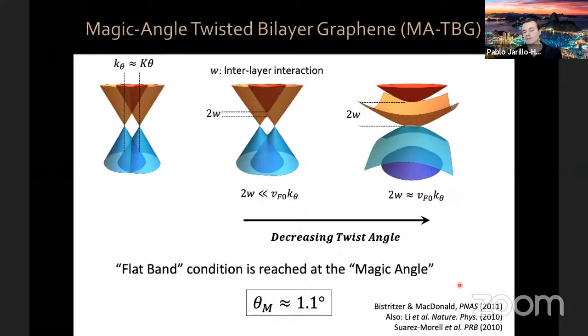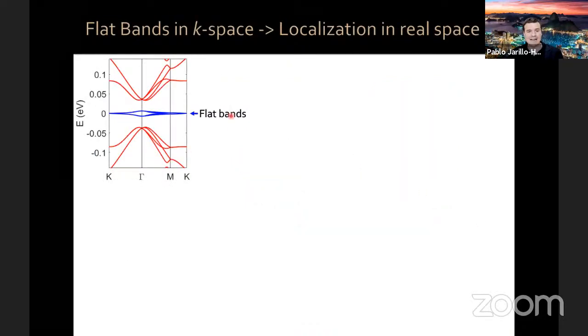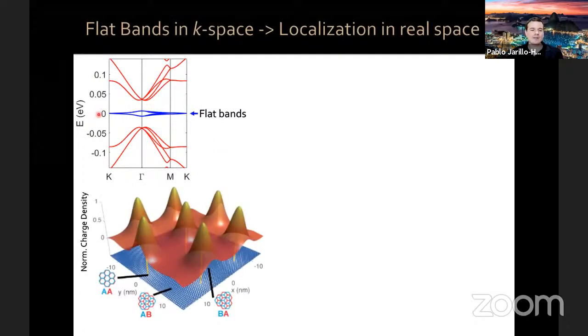Now, I should mention that there was very interesting experimental and theoretical work at about the same time, a little bit earlier actually, by the group of Eva Andrei and by the theory group of Eric Suárez Morell, where they already saw that indeed there was this formation of flat bands. This is an actual calculation of those flat bands in energy versus momentum. Flat in momentum space means highly peaked, highly localized in real space. To go from reciprocal space to real space, you just have to do the Fourier transform. So when you have electrons in these flat bands, they happen to be localized.